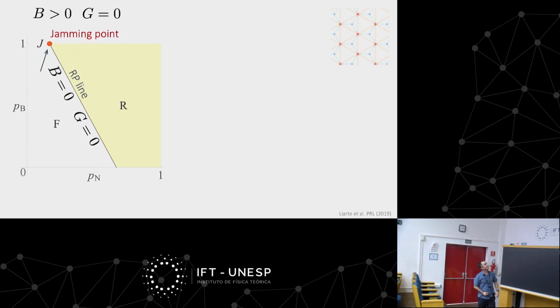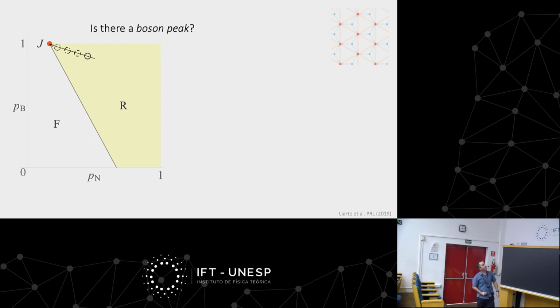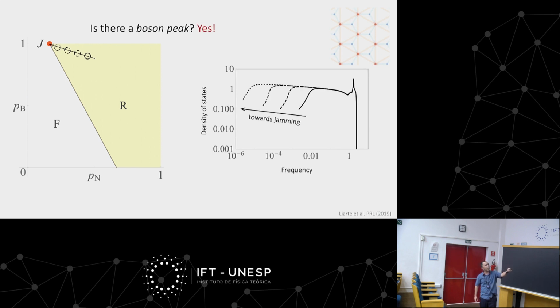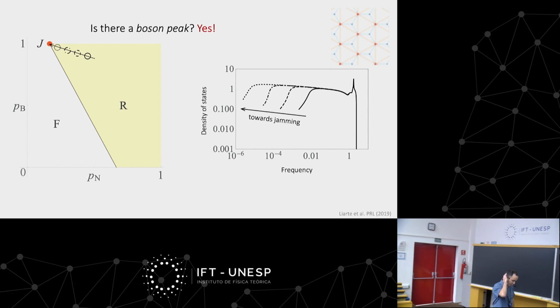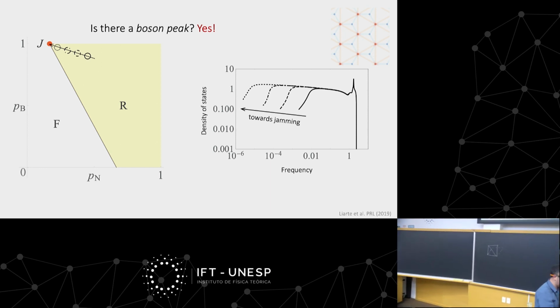All right, so I told you about this phase diagram, and you end up at a jamming point. I told you about the boson peak at the beginning of my talk when I talked about jamming, and you can ask whether or not this kind of network structure would also have a boson peak. And of course, as you get close to this jamming point, the answer is yes. You can plot the density of states as a function of frequency, and in fact, you have some enhancement of the population of low energy modes associated with this boson peak. That's much like what you have for jamming of spheres.